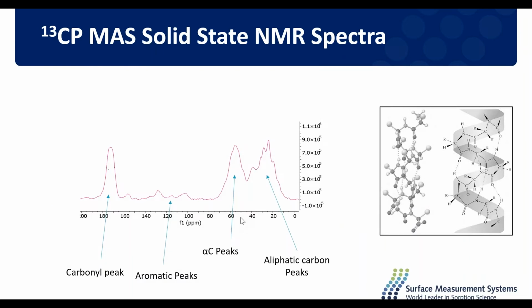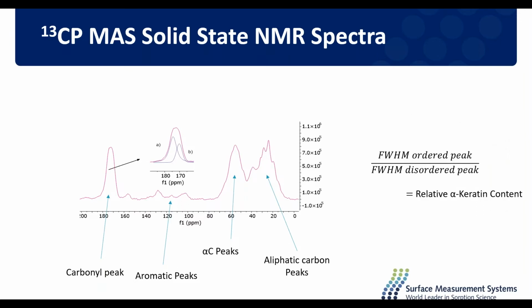Another really nice feature of this spectra is that carbonyl peak. So as I said, it is made from all the different carbonyls, orientations and forms in this keratin structure, and we can deconvolute this peak using MestReNova software to identify those contributions. So the peak labelled A is the ordered keratin made from alpha keratin, and the peak labelled B is the contributions from the disordered keratin, this being beta sheet keratin, but also the coiled coil conformational keratin. And we can make a ratio of these peaks using the full width half max of the peaks. And this gives us a relative alpha keratin content, which is a good measure of order in the samples.